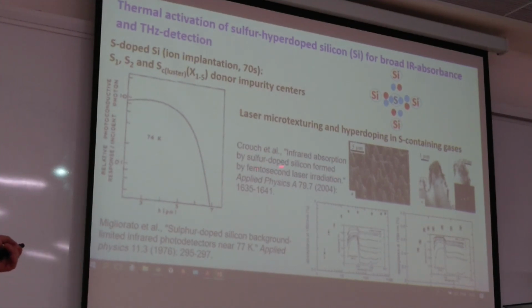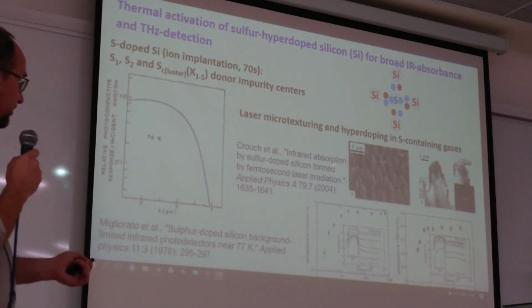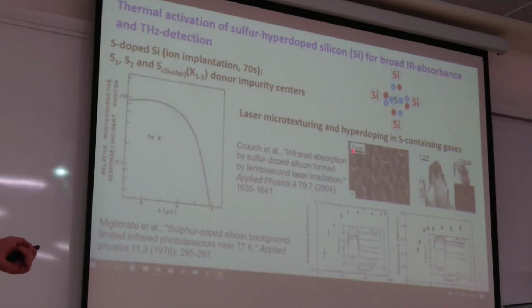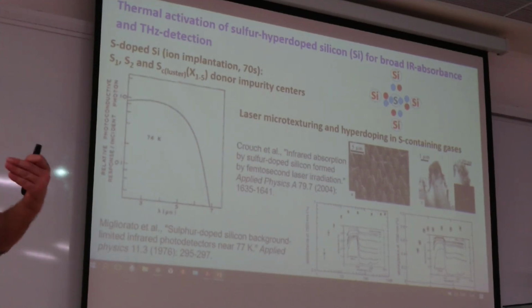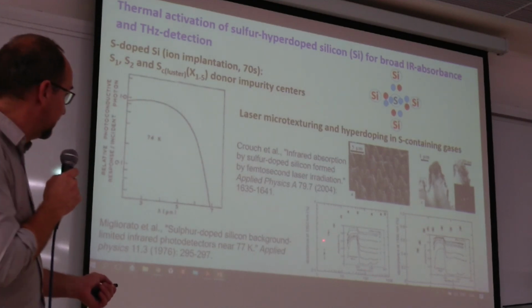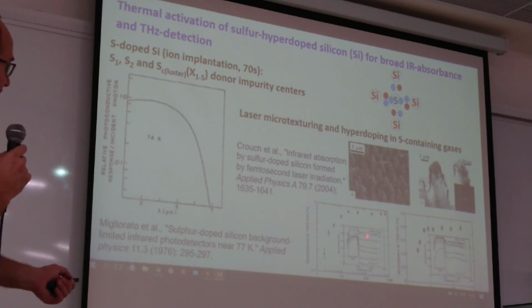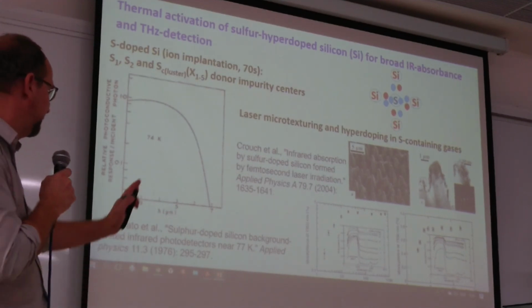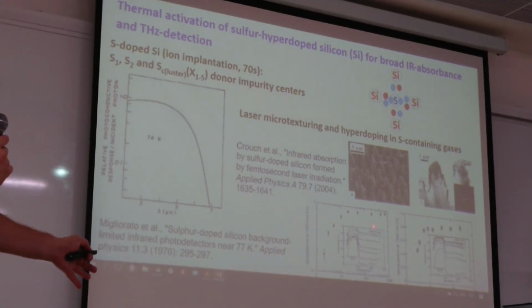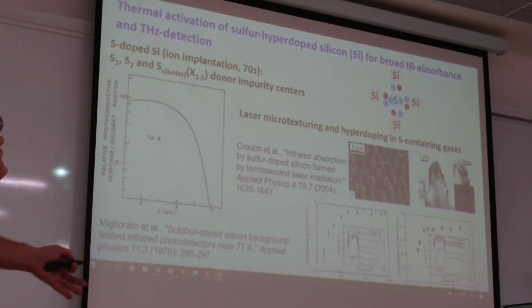It was demonstrated by people from Harvard University in the United States. Exposure of a silicon surface to femtosecond lasers produces microstructures, and the microstructures are doped with sulfur. They used sulfur gases like sulfur hexafluoride and other gases. The gas molecules, when they hit the hot silicon surface, dissociate and sulfur enters the silicon. So they have demonstrated, sorry for the not very good quality, an increase of absorption in the near infrared range up to 2 and 2.5 microns.